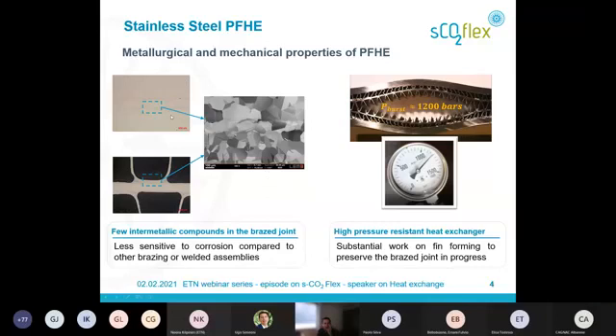For the project, we have this particular to be sure that we have the base material, stainless steel, and a brazing alloy. It's a nickel alloy, and you can see at the end, after the brazing part, we cannot even distinguish the difference between the stainless steel and the nickel alloy. So this is between the parting sheet and the bars, and here it's between the parting sheet and the fins. And so we have few intermetallic compounds in the braze joint, so it's less sensitive to corrosion, and it can be compared to other brazing or welded assemblies.